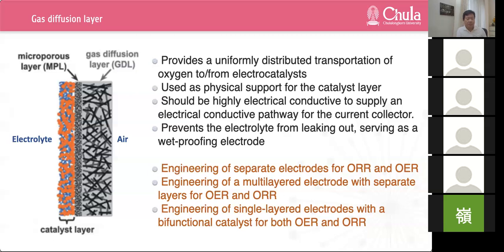So GDL should be highly porous, hydrophobic in nature, and thin to allow oxygen transportation to the electrocatalyst. Recently, the design of gas diffusion air electrode consists of several PTFE-bonded carbon layers with two interpenetrating microchannels of hydrophobic and hydrophilic layers on current collector layers, which are nickel, stainless steel mesh, titanium mesh, nickel copper foam, and carbon.